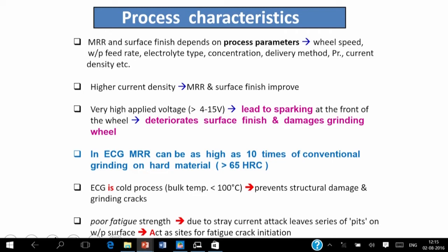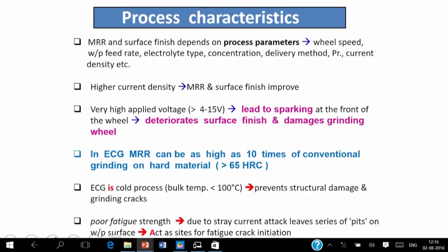So it is a bulk process, it is a cold process. Here the temperature does not go beyond 100 degrees centigrade, because the electrolyte is forced to flow in between the grinding wheel and the workpiece, so whatever heat is generated is taken outside. The temperature is automatically controlled. If it goes beyond that, there is structural damage or grinding cracks may be generated.